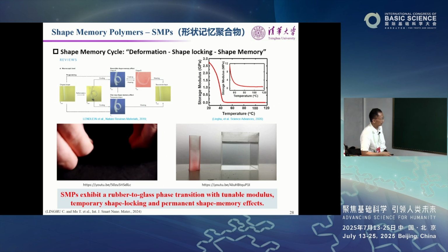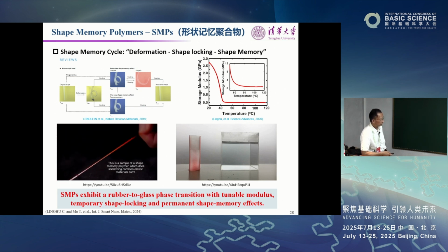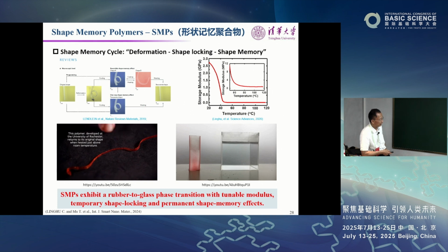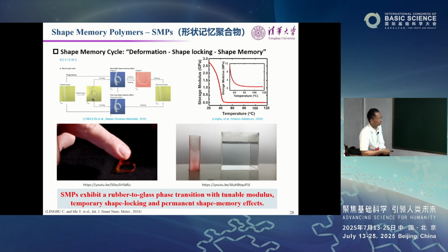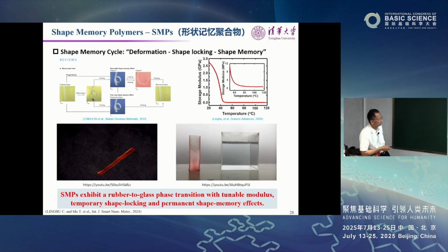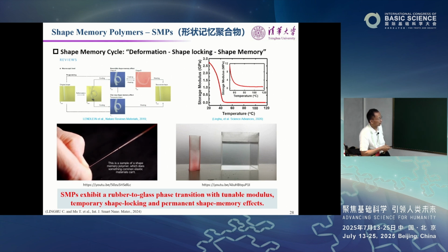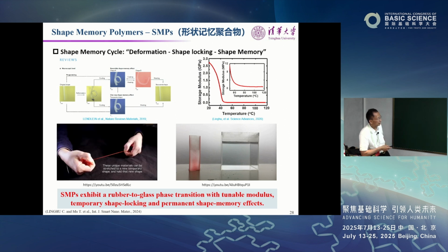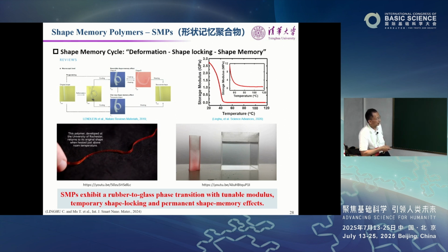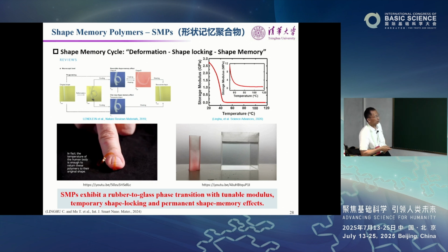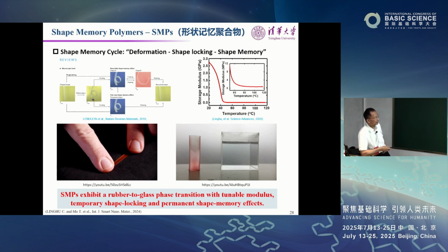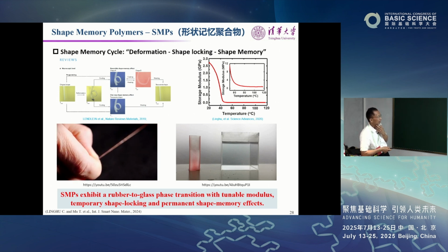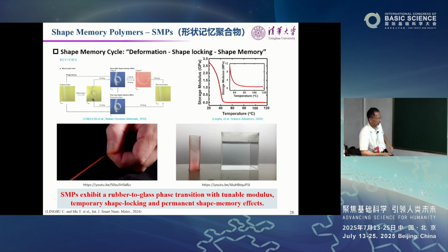Okay, so let me explain this one you're seeing here. You deform above Tg, all right? Then you cool it down, and you can see this length remains. Then we want to restore the original shape, you just heat it up. Okay, so this material exhibits three phenomena: deformation, shape locking, and shape memory. Deformation is highly deformable above Tg. When you cool it down below Tg, the shape can be temporarily locked. So elastic energy can be frozen temporarily, but the energy is not lost. When you want to release energy, you just heat it up above Tg, and you just recover the original shape.